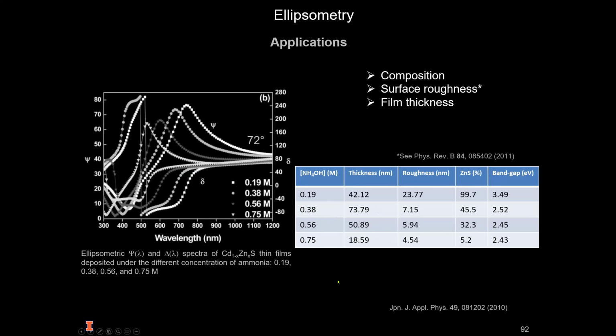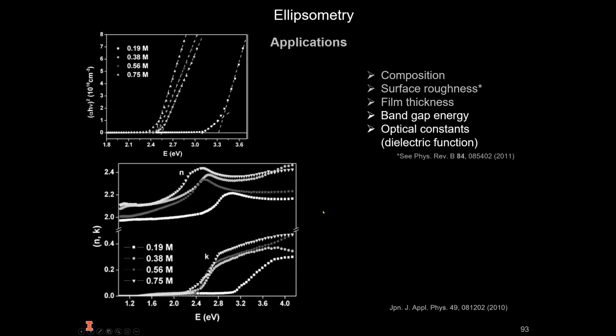We can also use ellipsometry to measure the optical constants of each film analyzed, like they did here for the cadmium zinc sulfide. And here they also verified the optical constants they obtained by measuring spectrophotometry as a complementary technique.